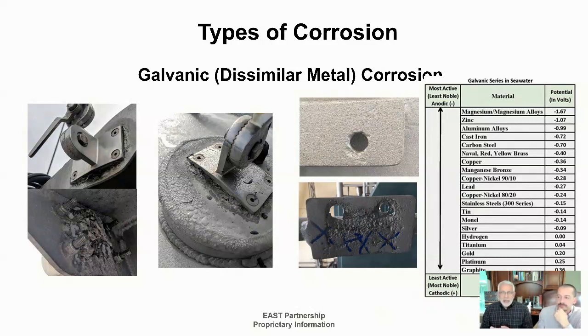So if you start having this failure, everybody runs to stainless steel hardware, no matter what they're putting together. That could be okay, or that can be causing the issues. If it's a real dry environment and they're not too far apart on that galvanic scale, the rate will be super slow, and you may not have a problem for quite some time. If that environment is moist and they are far apart, like stainless and aluminum are, you start to have these issues. The picture on the top left shows an antenna mount on an aluminum surface. It is made of stainless steel, and the hardware is stainless.